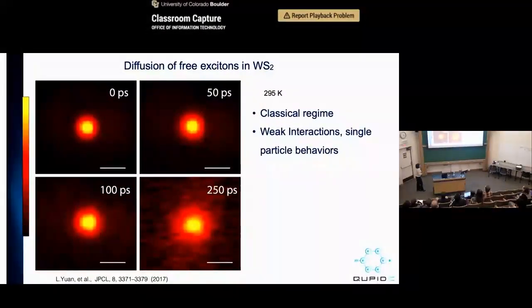Anyway, I'm going to start with an example in the classical or semi-classical limit, where this exciton is just freely moving around and diffusing. This is an example of an exciton in a single layer tungsten disulfide. We are imaging at the exciton resonance, which in this case is about 2 electron volts. At 0 time, the scale bar is 1 micron, and what we see is the pump image, where you inject the exciton density with the pump. It's a Gaussian pulse around half a micron across.